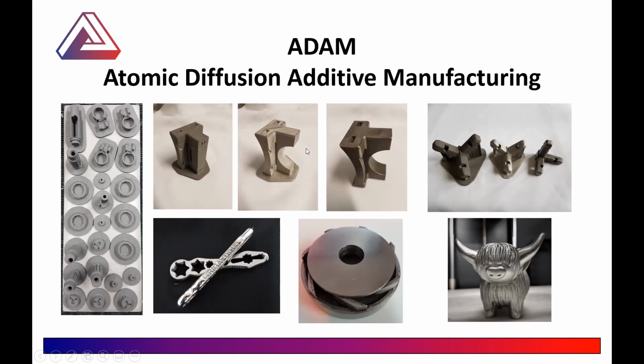What you can't really see from these photographs is an important factor. The finished component and the green part straight off the printer, as you can see in the size there, is actually around about 19 to 20% smaller. So when we model it into the software, it actually prints the part off about 19-20% larger than the finished component. It's all done by the software, by fancy calculations to compensate for the wall thicknesses and thick areas, etc., so that when it comes out of the sinter process, you're hitting shape.